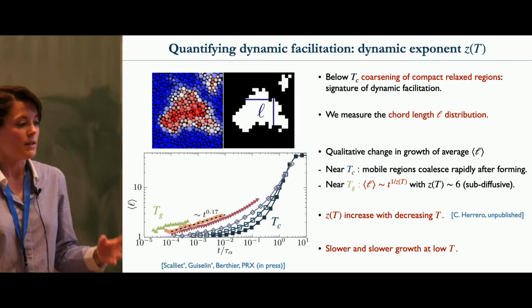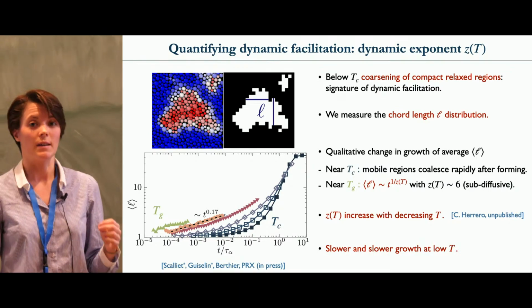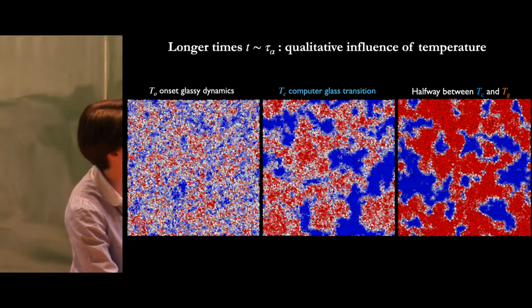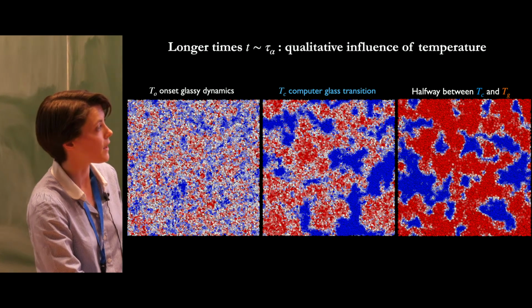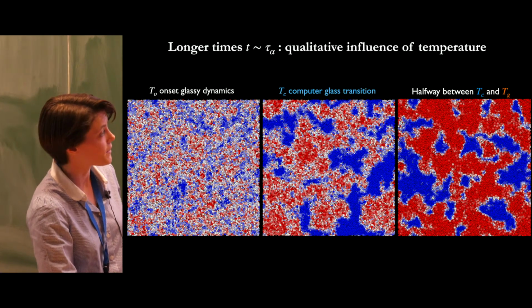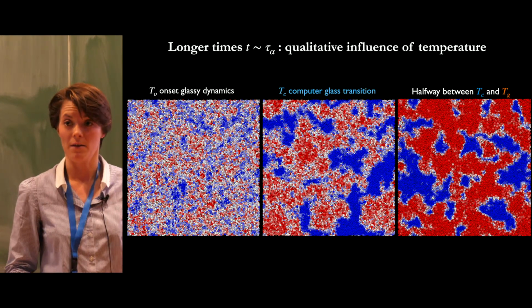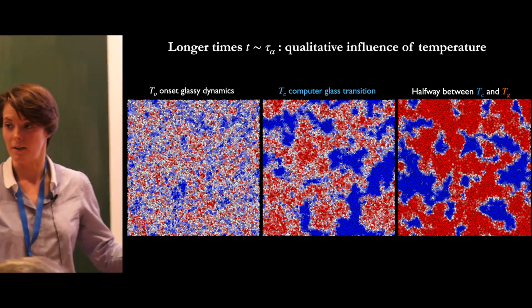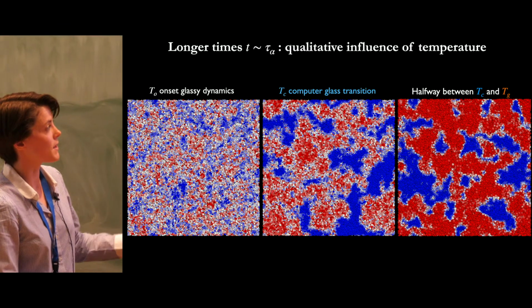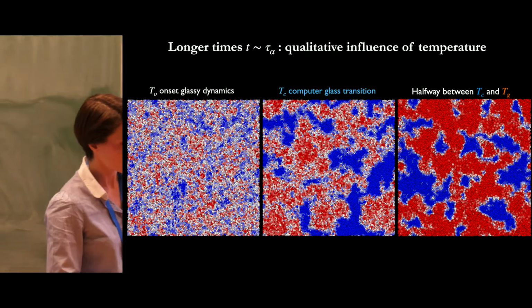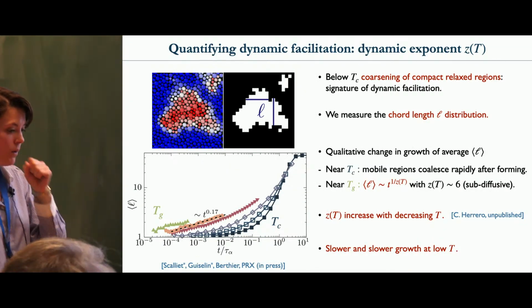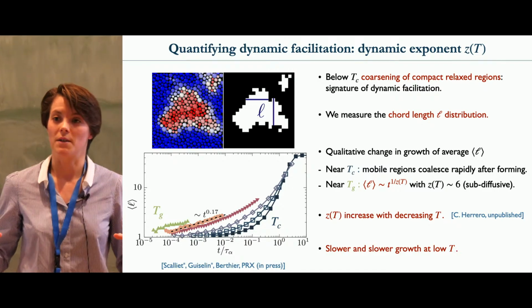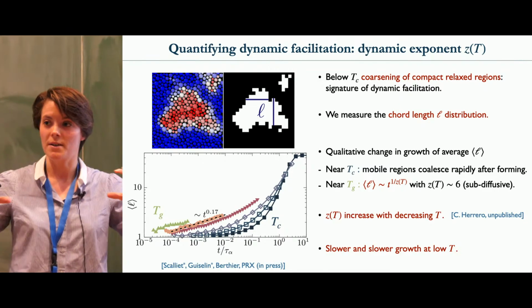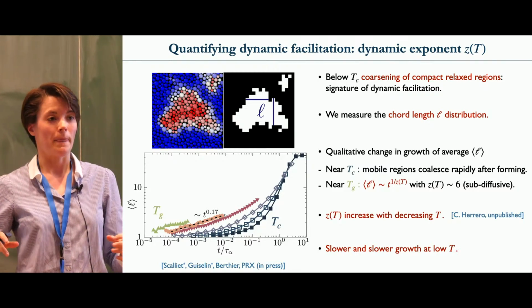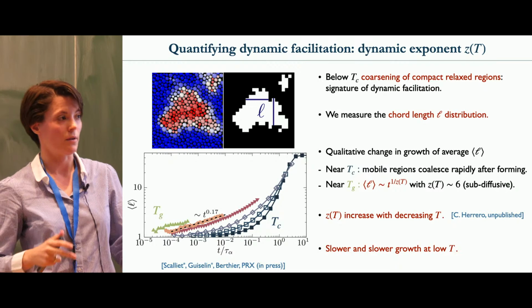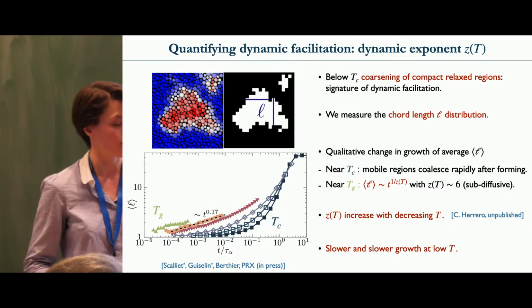So in this slide, what I want to show you is that at these low temperatures, you have very clear regions that have relaxed in red, and here you can actually directly measure their size. I think that by eye you can see this size. If I ask you what is the typical size, you would say, well, maybe 1 particle or 2. Here we were interested in quantifying this idea of dynamic facilitation, the fact that the dynamics spreads in space over time, and to try and see if it's diffusive or subdiffusive, or really quantify this sort of dynamics.